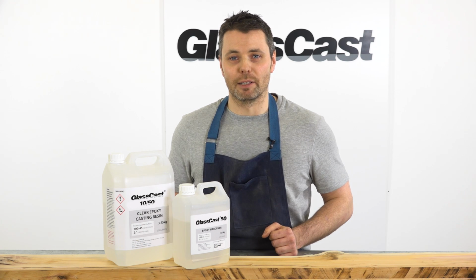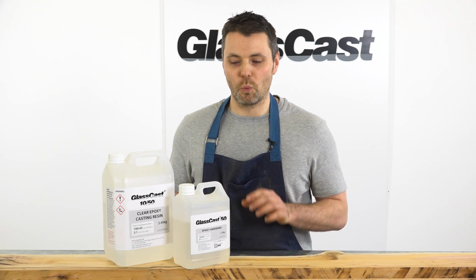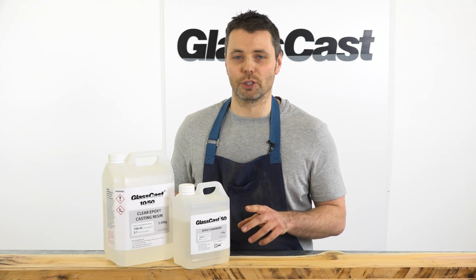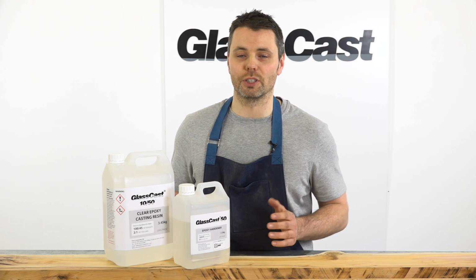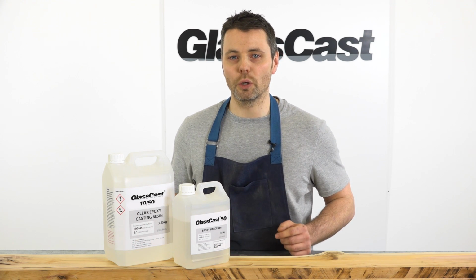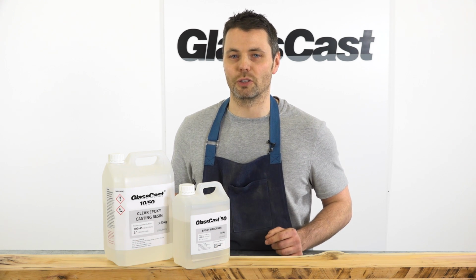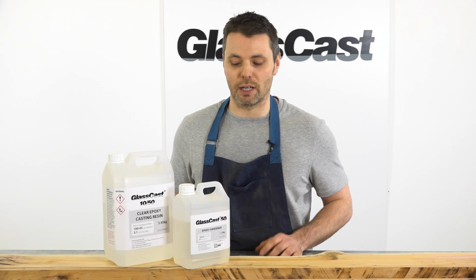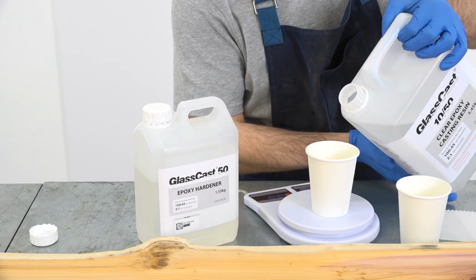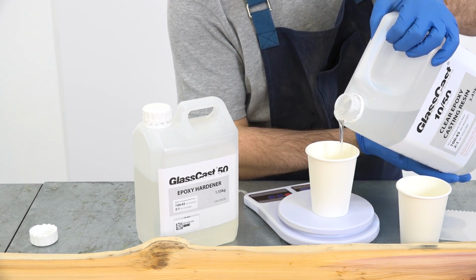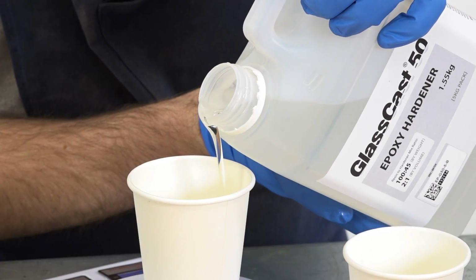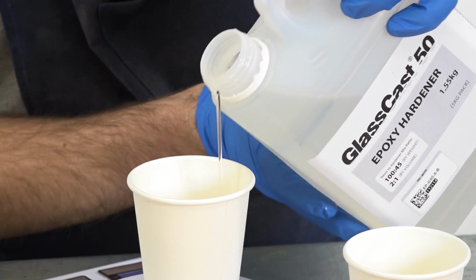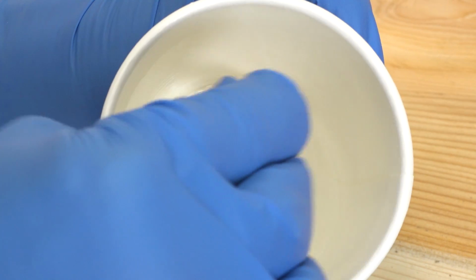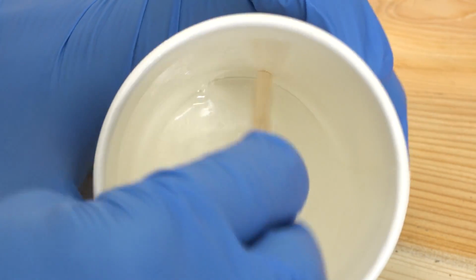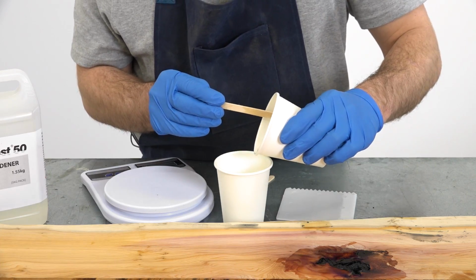Mix ratios vary between the GlassCast products. With the GlassCast 50, you've got two options. You can mix by weight, which is 100 parts to 45, or you can mix by volume, and that's at 2 to 1. Whichever you choose is fine, but just make sure you get that measurement as accurate as possible. For this small mix, I'm going to use the 100 to 45 by weight mix ratio. I'll keep things simple with 100 grams of resin and 45 grams of hardener.